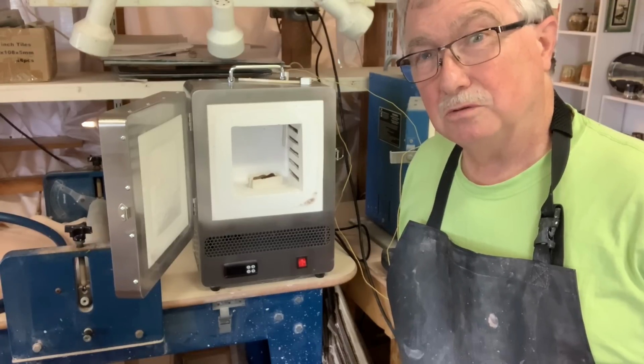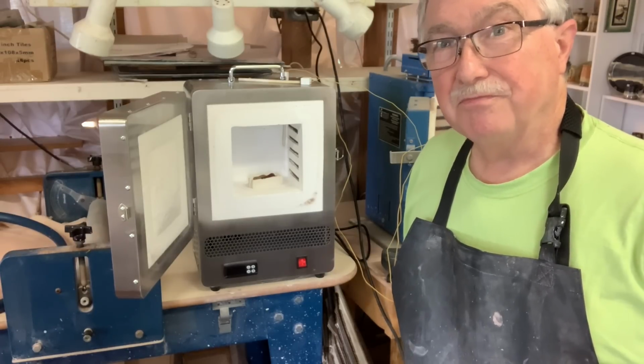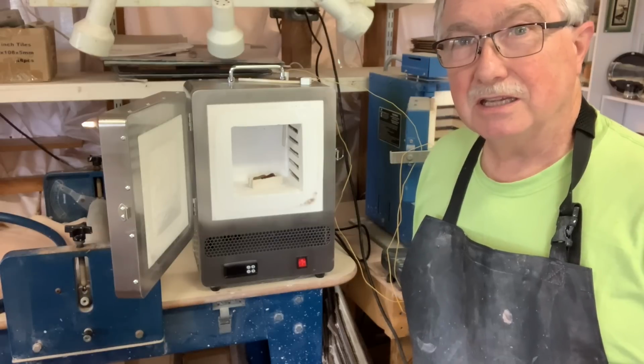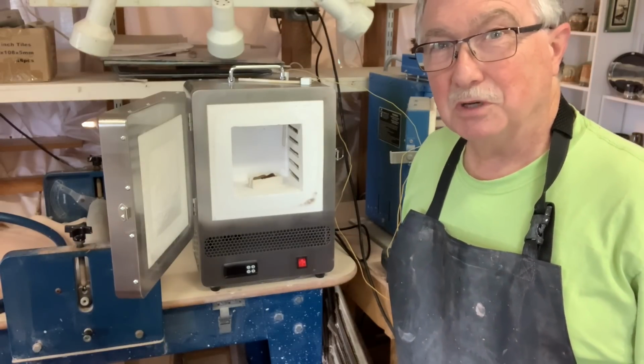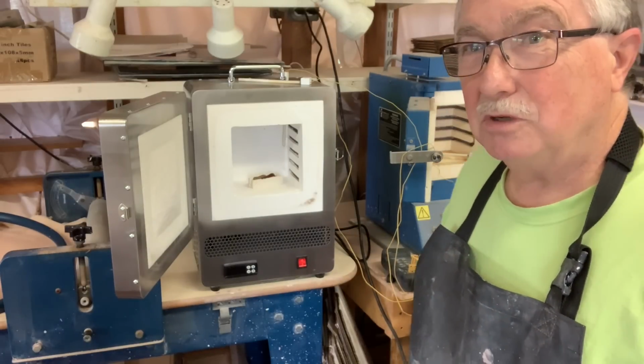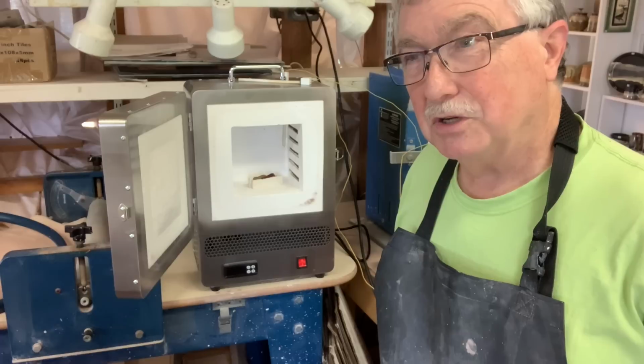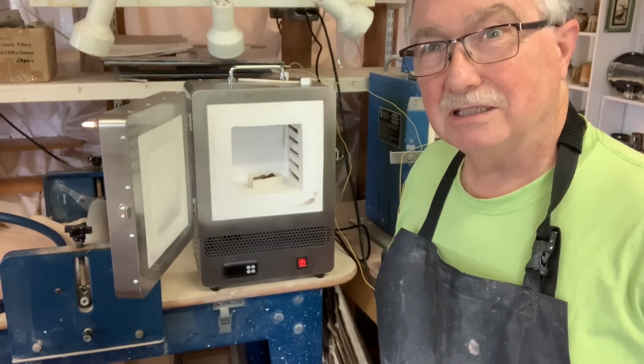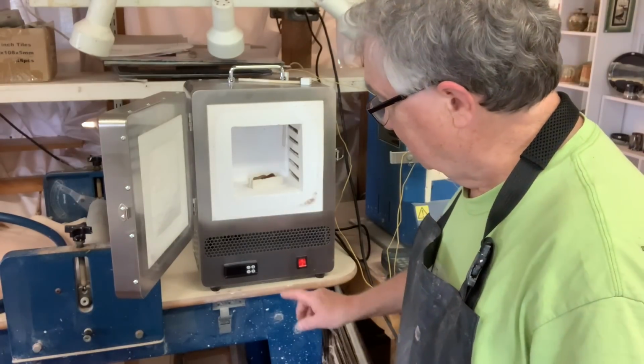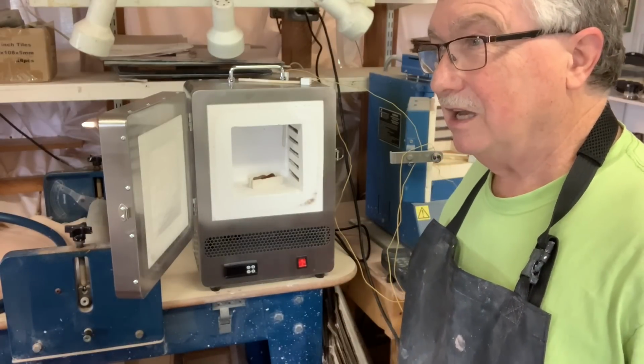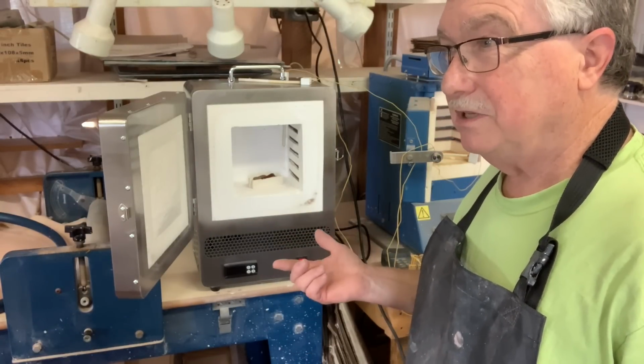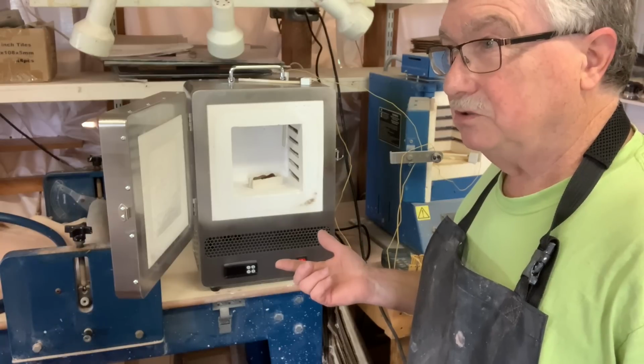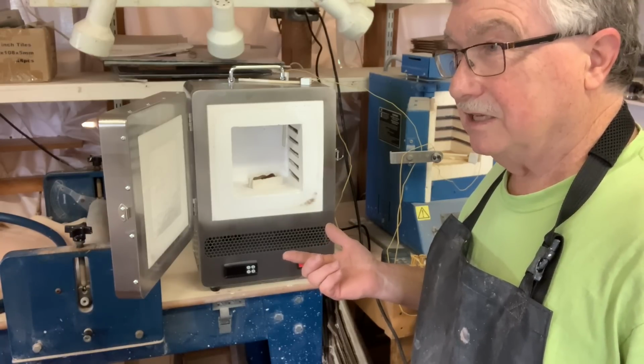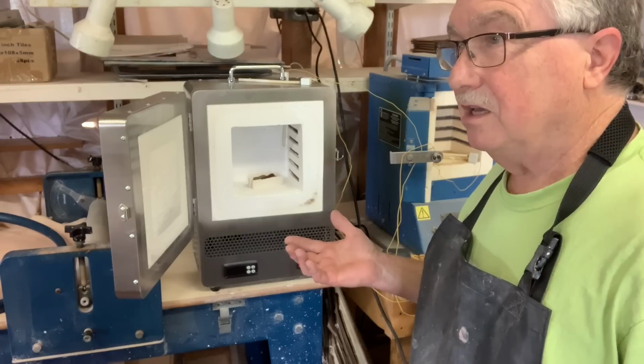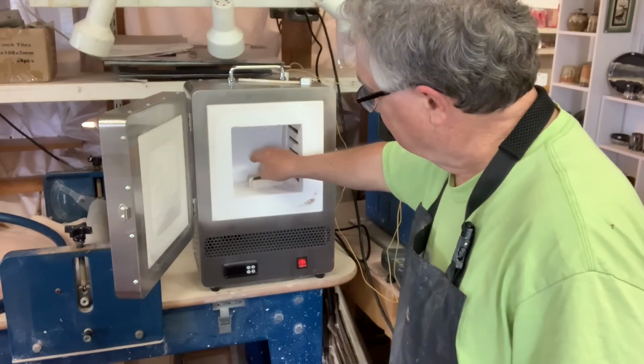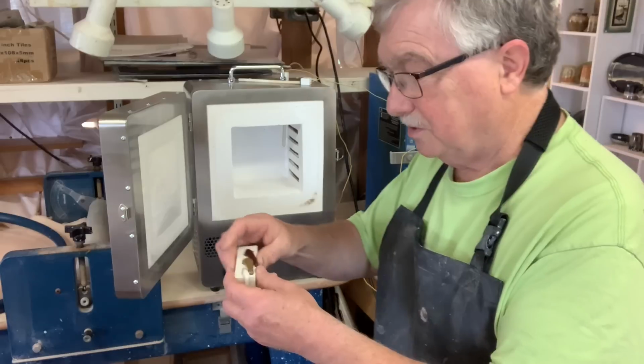And basically it's cooled down in about 4.5 hours, I guess. So you could do a couple of firings a day in this kiln, get a mug in the morning, mug in the afternoon. But the problem is the thermocouple is not reading accurately. So I set this, and I put 2 cones in, 1023 centigrade. Cone 6 should have bent over, because that's the normal way it would bend over at that temperature. And it was reading 1023, and is this too hot? No, it's not too bad.